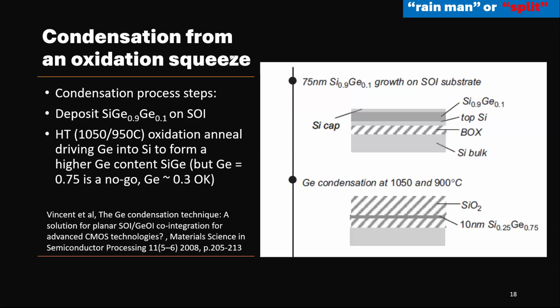And this is called condensation. What it means is that we put a SiGe layer, say 10% germanium, on top of SOI. It's a top silicon. And condensation means you just heat up to a very high temperature, say 1050 and 900, for hours, and you oxidize the top layer. We mentioned that it will push germanium down. When you oxidize it, it will form SiO2 and push the germanium down, and germanium will interact with the silicon here. It will be combined with it.